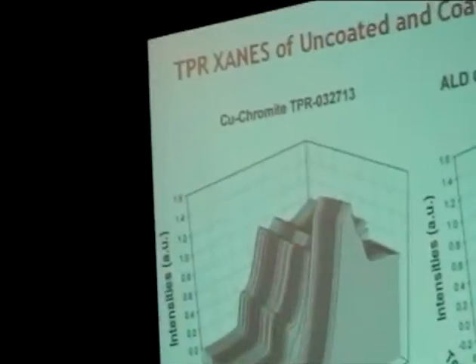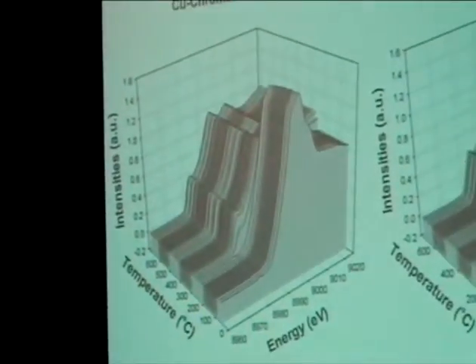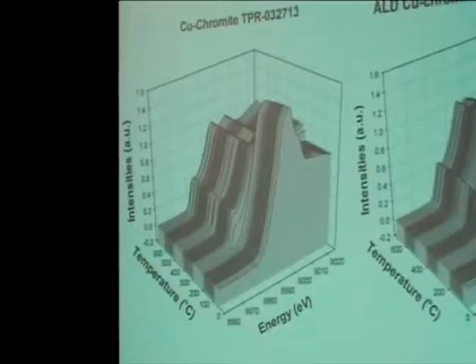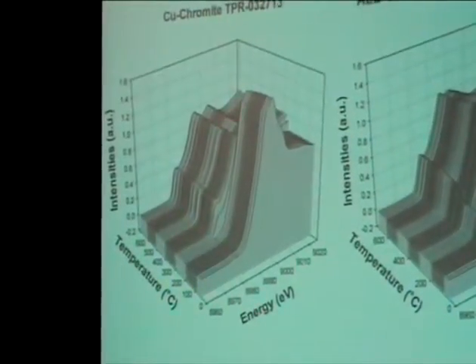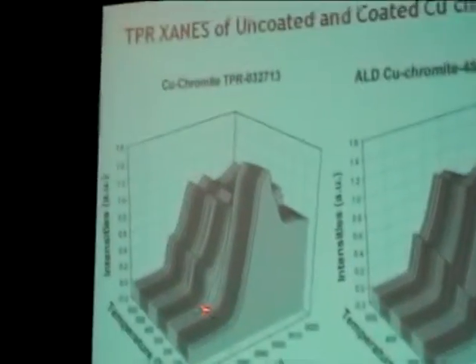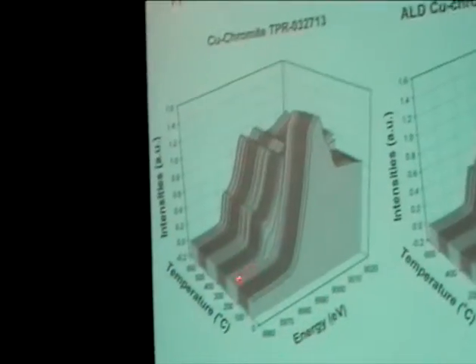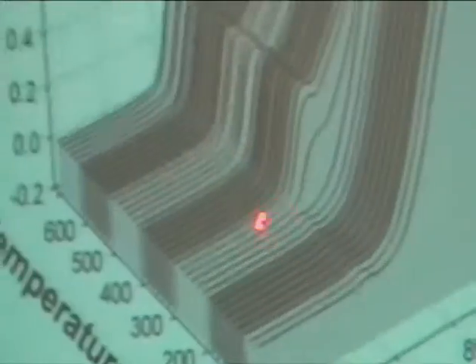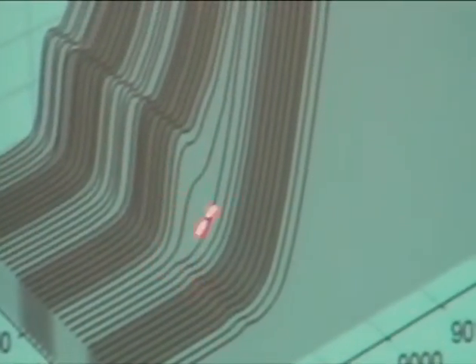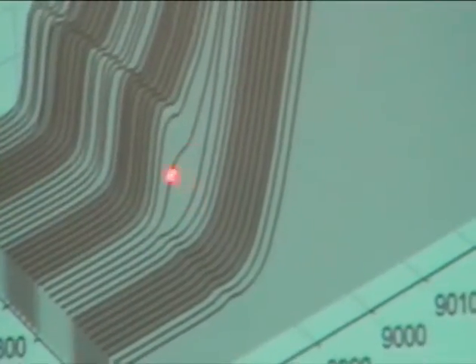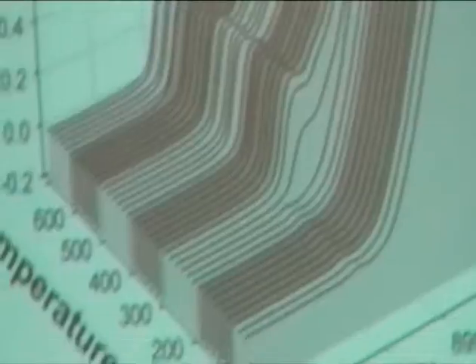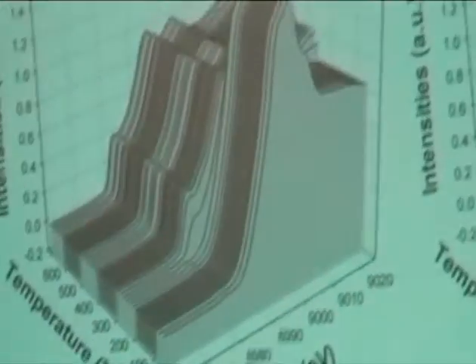This initial material, as I said, starts out as copper 1 material, and we see the onset of reduction at around 270 degrees C. That's that peak right there, and that's done by about 300 degrees Celsius on this scale here.